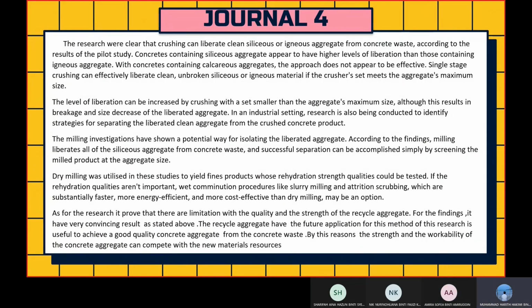The fourth journal, the research were clear that crushing can liberate clean siliceous or igneous aggregate from concrete waste. According to the result of the pilot study, concrete containing siliceous aggregate appeared to have higher levels of liberation than those containing igneous aggregate. With concrete containing calcareous aggregate, the approach does not appear to be effective. Single-stage crushing liberate clean, unbroken siliceous or igneous material if the crusher set meets the aggregate maximum size.